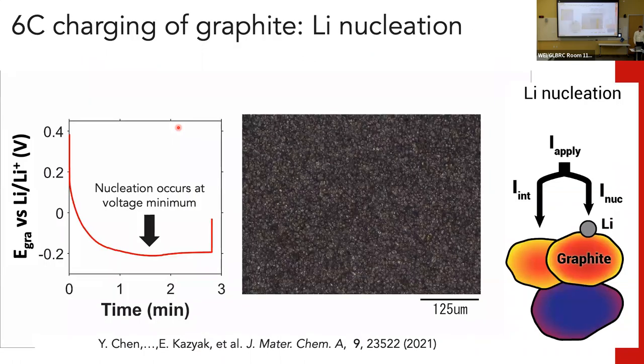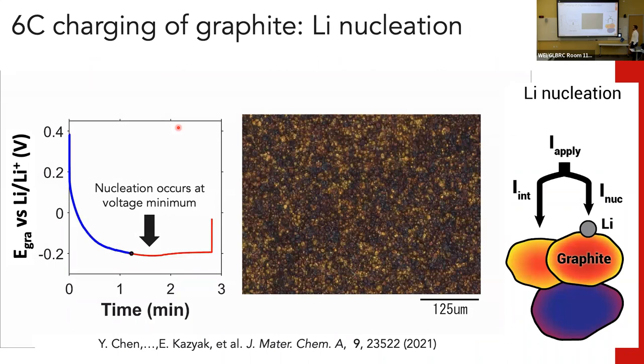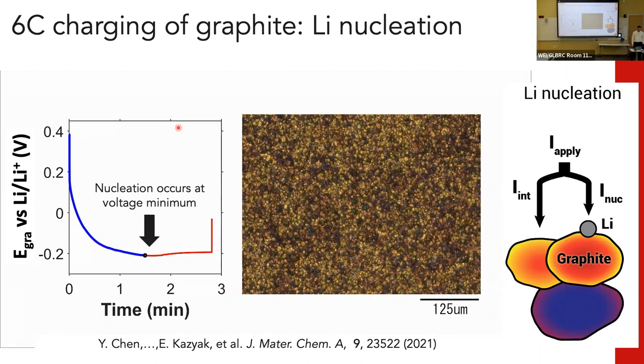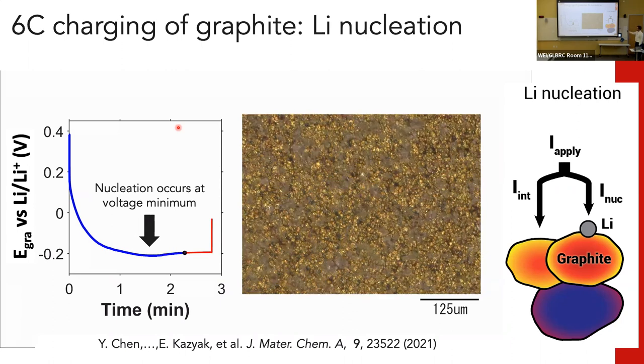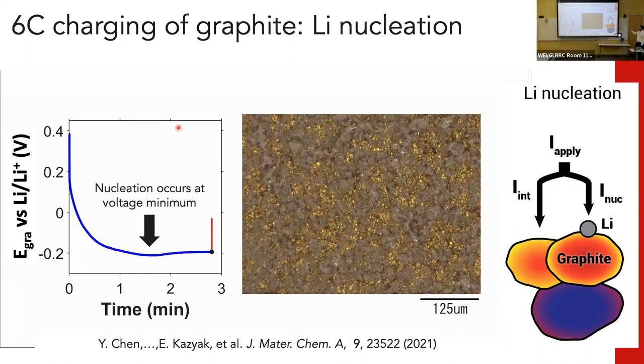All right. So what does this look like in real life? Looks something like this, where as we start charging our battery, this is at 6C, so this is a 10-minute charge. Graphite has a nice property where it changes colors as you put lithium in it. So you can actually visually see state of charge in graphite. So these gold particles are now fully lithiated. But at a certain point, and in this controlled cell, we can actually measure how close to the potential of metallic lithium, or lithium-lithium plus, we are in this case. So we're actually below that potential, which means we can plate out lithium metal. And as we proceed, you indeed see these kind of silvery gray deposits of lithium metal accumulate on the surface of the graphite. So this is what we want to prevent.